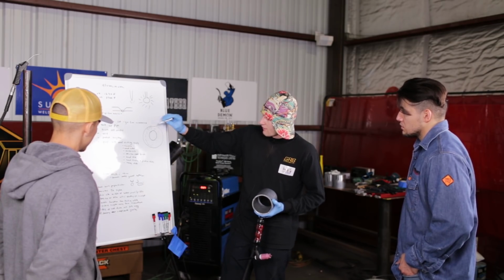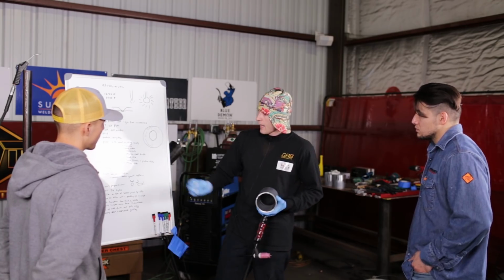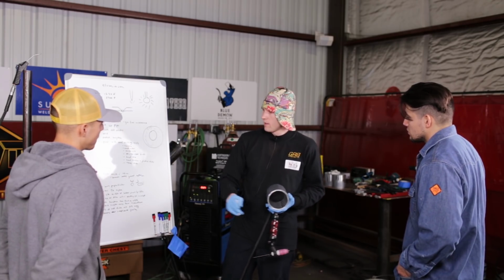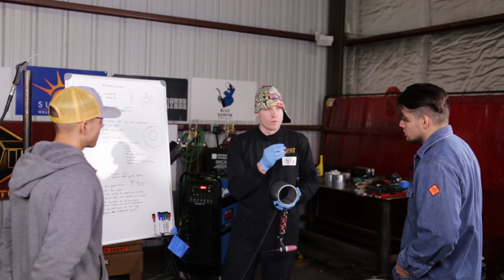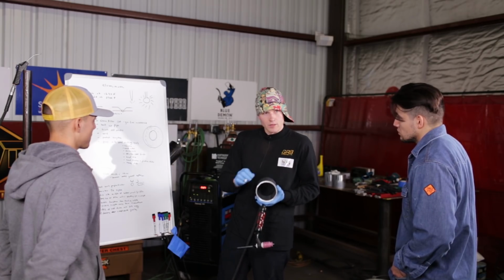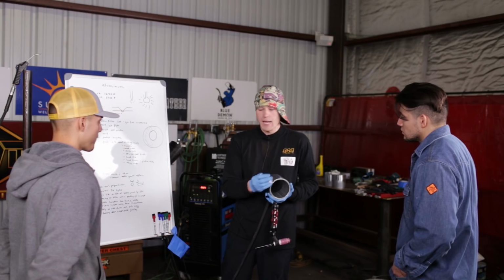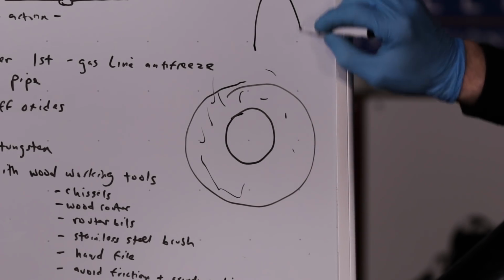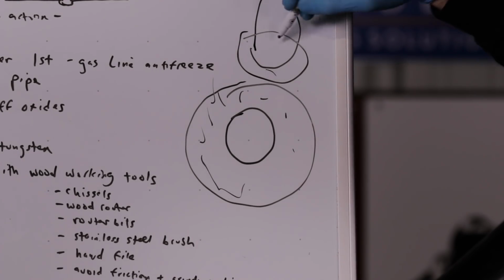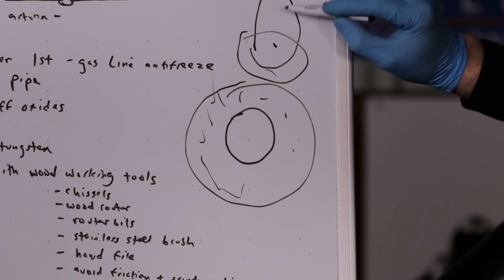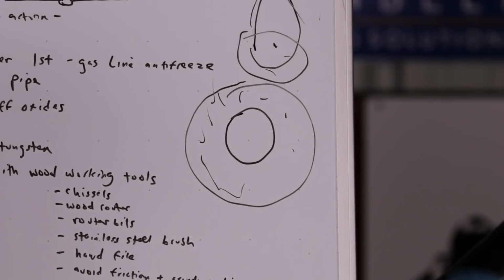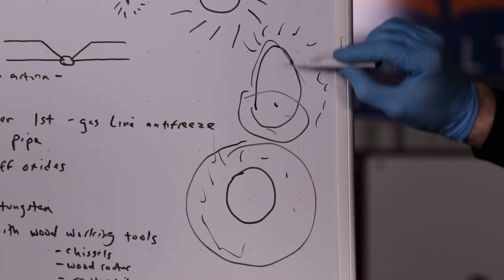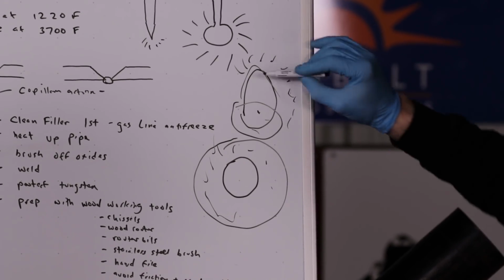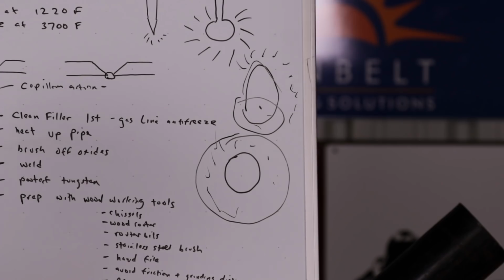But when it comes to aluminum, you want to hold everything perpendicular because you do not want to form any oxides ahead of the arc. When you start adding an inclination, say 5 degrees, 10 degrees, or even walking the cup, and a lot of times when guys are moving from different metals, carbon steel, etc., out of habit they start holding the torch at a little bit of an angle, and the weld puddle ends up going from round to slightly oblong, and the torch is down here. What you're actually doing is not only protecting the puddle down here, but also heating up the leading edge because the weld puddle is going oblong. You're heating up ahead of the arc, and it's starting to form oxide. So with an oblong weld puddle you have the formation of oxides, and you start welding over those oxides, and because they melt at a higher temperature than the base material, they end up as porosity in your weld zone.